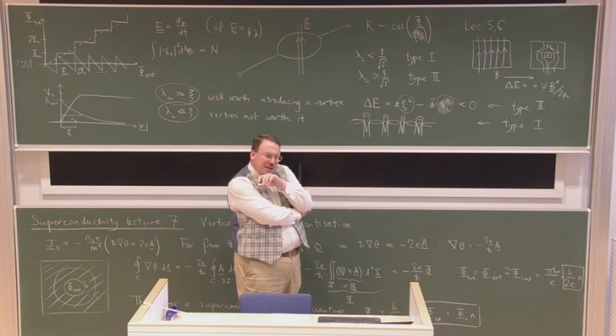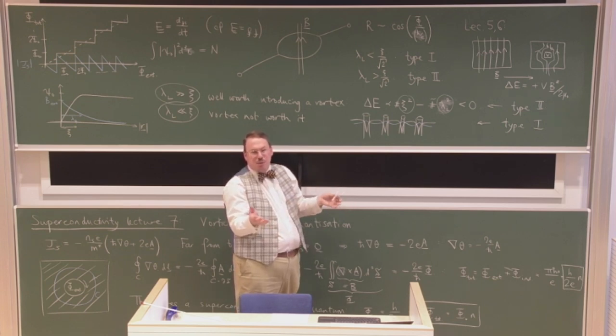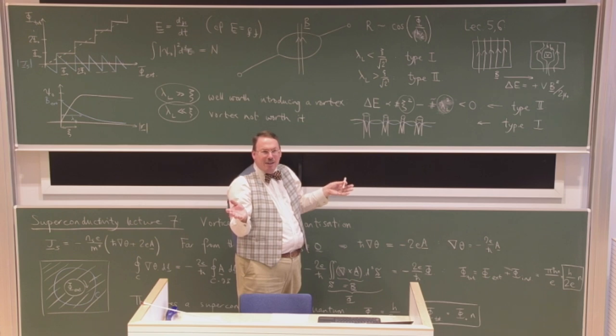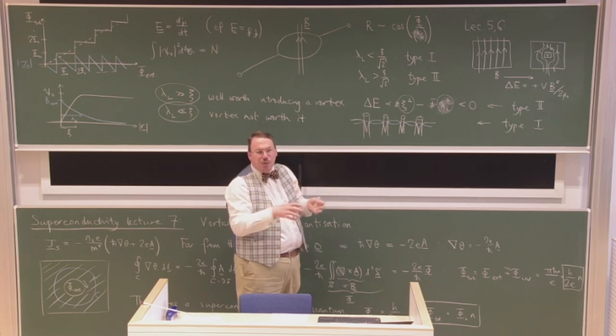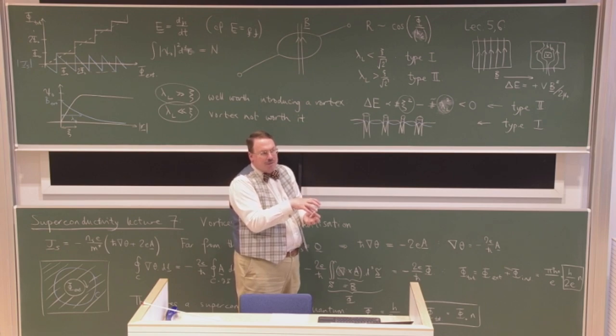And most of the time, if your superconductor formed out of a fairly robust Fermi liquid, then the nearest state in free energy is just going to be that Fermi liquid in a field. So in conventional cases where there's a phonon-driven superconducting instability on the background of an otherwise perfectly good metal, the expectation would be that the vortex core would be described by Fermi liquid theory insofar as it's large enough for Fermi liquid theory to make sense.